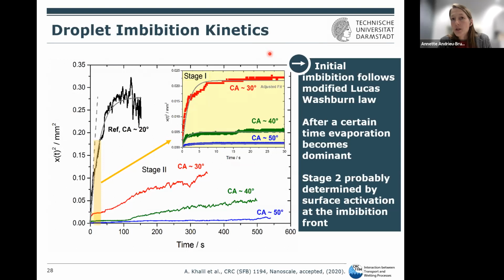This rheology thing, we only used water in these experiments. So that's a Newtonian fluid. And you're right that you have these condensation layers and that there's literature on the adsorbed water that's quite strongly adsorbed. But so far I don't have information on the changing rheology of water in these pores, which for sure will happen directly at the surface. But I'm not sure that this is then determining for the fluid imbibition, because maybe you can imagine this adsorbed layer as relatively constant. But I'm not a chemist looking at these flow phenomena.